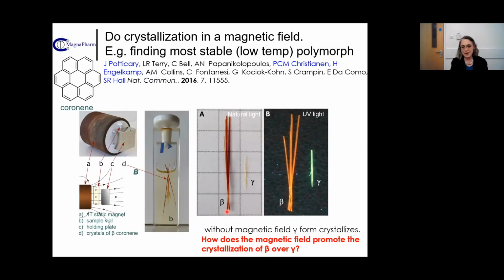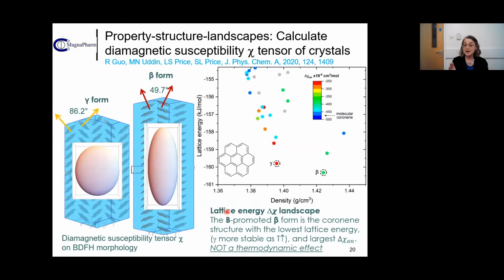And so we had the job as theorists of having to try and explain this. And, remember, these are organic molecules. They're not paramagnetic. All electrons are paired. The diamagnetic effects of crystals are tiny. And so we had a theory of trying to get the diamagnetic effects of different crystal packings, where the effects of the molecules are sort of cancelling out in the crystal structure. So it's a tensor property. And we developed the theory of predicting it. And yes, the beta form is more affected in the anisotropy of its reaction to a magnetic field than the gamma form.